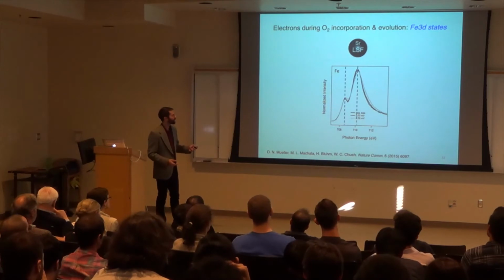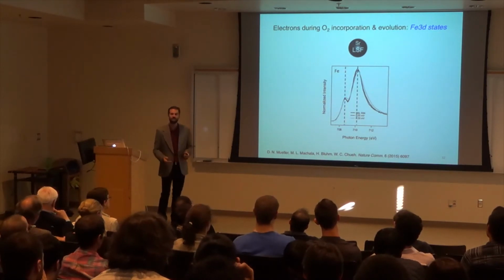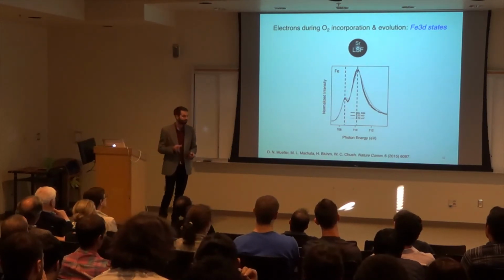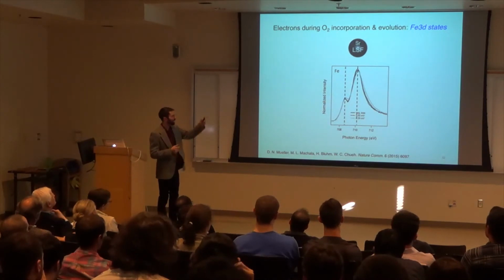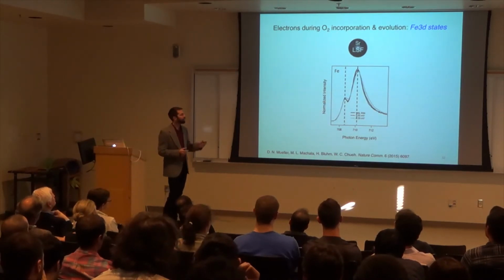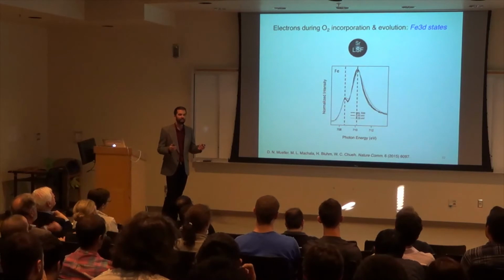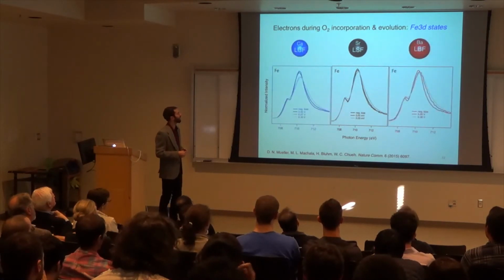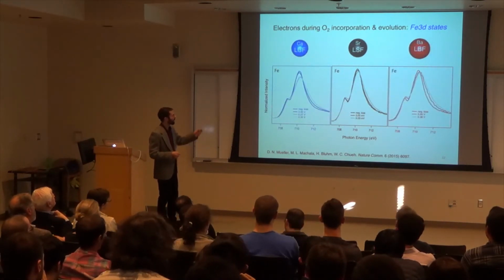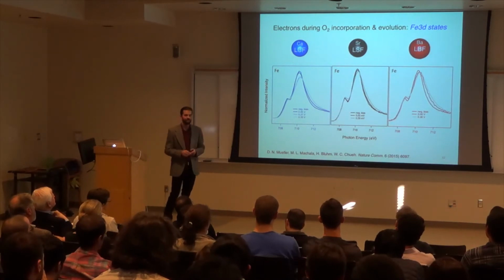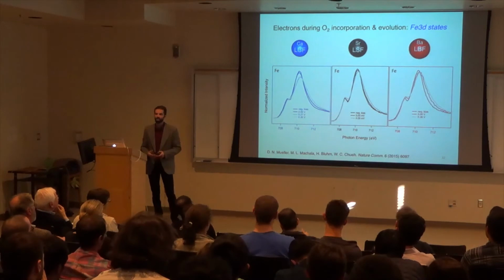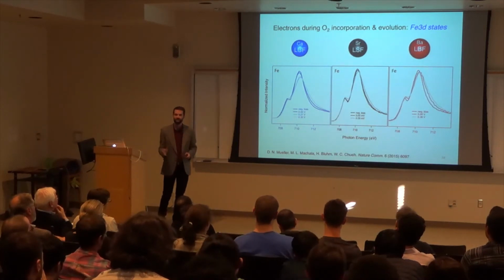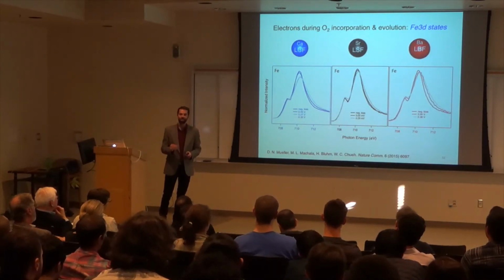And if it were to change, we would see pretty significant shifts in these two peaks. But what we see right here is that not much is changing. And if we extend this to the other cations, the lanthanum or the calcium and the barium, we see that the spectra aren't changing significantly as you try to drive oxygen in and out and try to change the transition metal oxidation state.